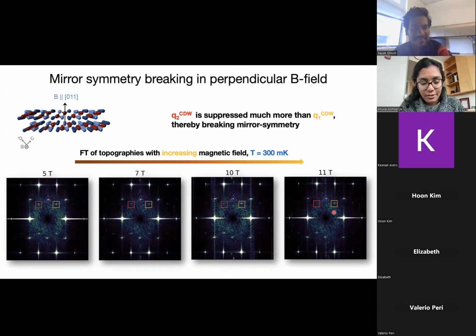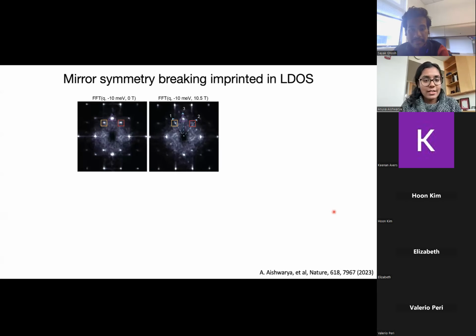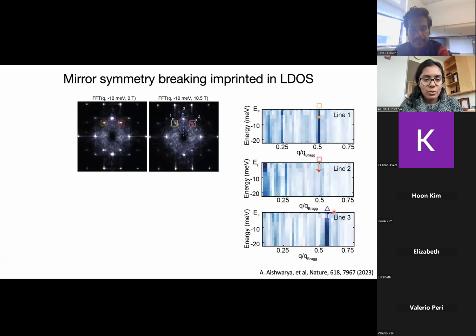But this is from the topography. So we want to see what the electrons are doing and if this mirror symmetry breaking is actually imprinted on the local density of states. So that's what we set out to do. Now I'm going to take line cuts in Fourier space as a function of energy at 10.5 Tesla. So these are the 3 plots. You can see that in the red square, there's no signal from the CDW, which means that this mirror symmetry breaking is actually imprinted on the density of states.